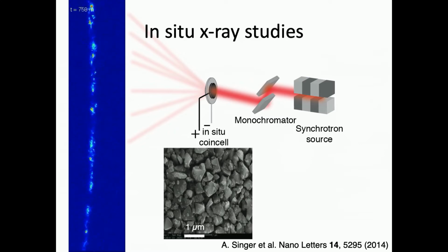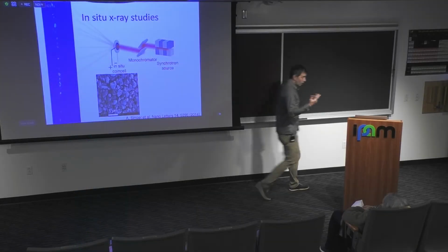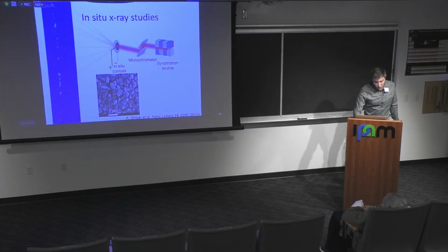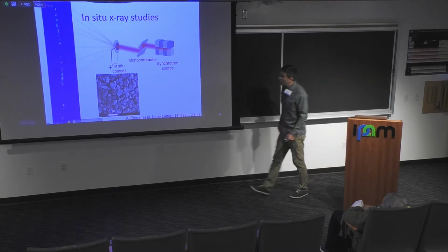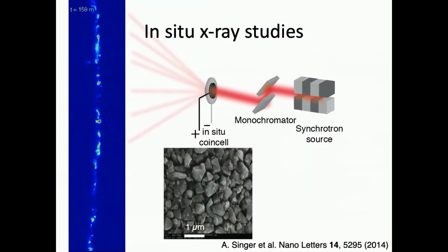There is a phase transition. That's why you see a jump from one Q vector to another. So all of you who think in reciprocal space will understand what's going on. And the cool thing here is that we can watch it and try to analyze it in many different ways. I'll play it again. The other thing is you can see that there is a little bit of a hysteresis, since the process working one way is not the same as it's working the other way.